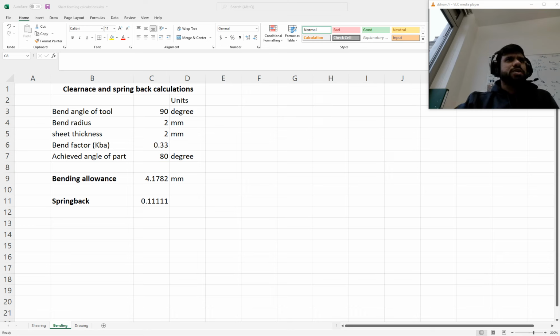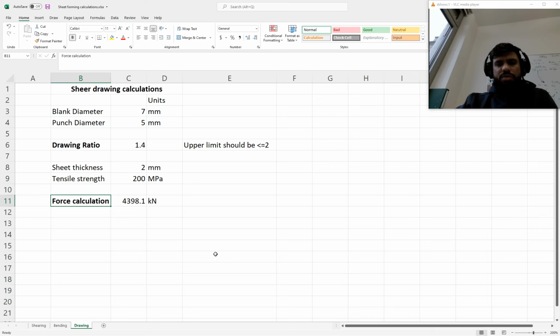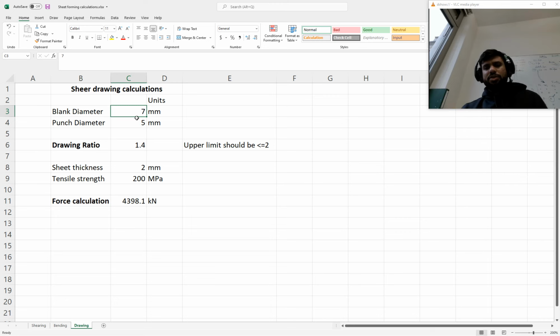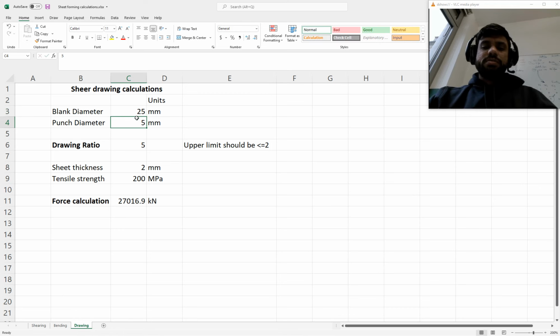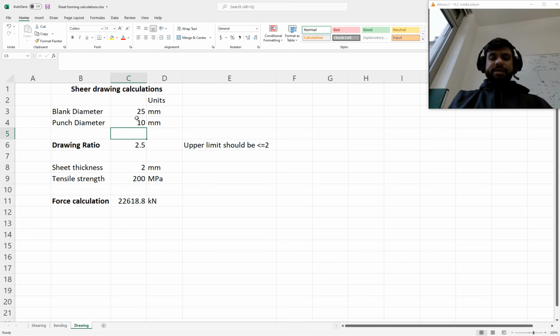So what you can do is continue using these sheets. Let me show you an example of a drawing process where it is quite a simple calculation. There are very few inputs, but there is a lot which we are getting as an output. So if I say that the blank diameter is 25 millimeters and the punch diameter is 10 millimeters, the draw ratio is 2.5. And then here I have added a comment that the upper limit should be less than 2.